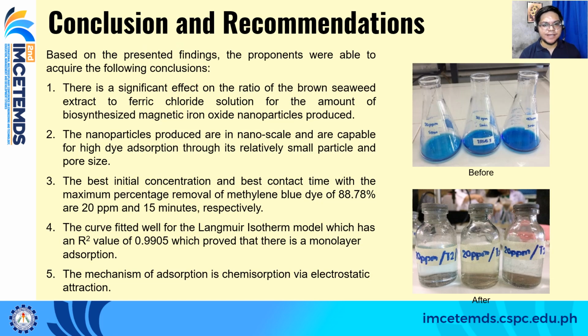Based on the presented findings, we were able to arrive at the following conclusions. First, there is a significant effect of the ratio of brown seaweed extract to ferric chloride solution on the amount of produced iron oxide nanoparticles. Second, the nanoparticles produced are in nanoscale and are capable of high dye adsorption through their relatively small particle and pore sizes. Number three, the best initial concentration and best contact time with the maximum percentage removal of methylene blue dye, 88.78%, are 20 ppm and 15 minutes respectively.